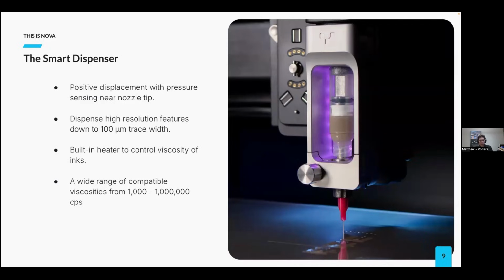Nova's Smart Dispenser is what allows Nova to dispense inks. It uses positive displacement with accurate fluid pressure sensing to dispense high resolution features down to 100 micron trace widths, and even smaller is still achievable depending on the material you use and the nozzle sizes. The Smart Dispenser has a built-in heater that stabilizes the viscosity of your ink, and so it's compatible with a wide range of materials.